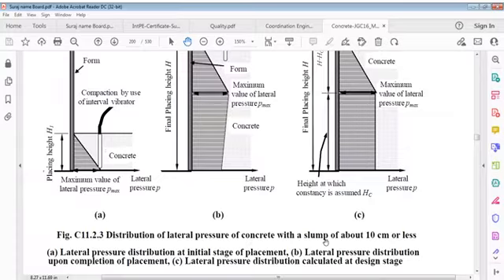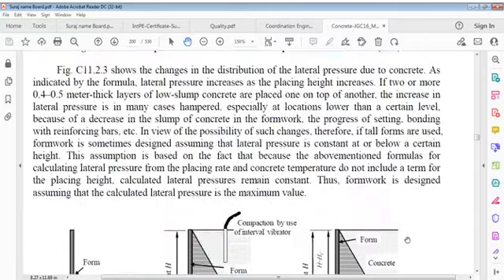A distribution of lateral pressure of concrete with slump of about 10 cm. Let's see this one. First it says this figure shows changes in distribution of lateral pressure due to concrete. What are the changes? As indicated by this formula, lateral pressure increases as placing height increases. Of course, that's true. If two or more 0.4 to 0.5 meter thick layers of low slump concrete are placed on top of another, increase in lateral pressure is in many cases hampered, especially at locations lower than a certain level, because of decrease in slump of concrete in formwork, progress of setting, bonding with reinforcing bars, etc.